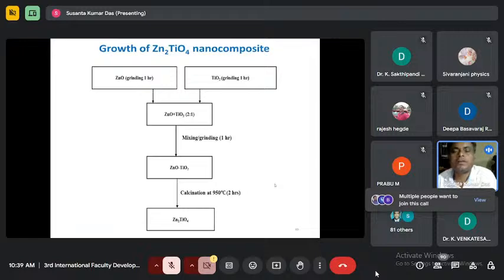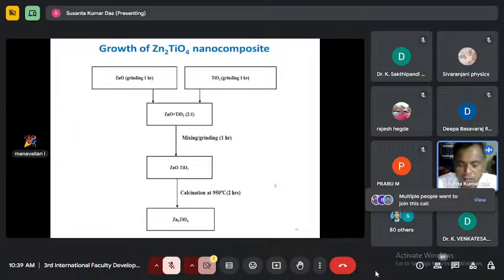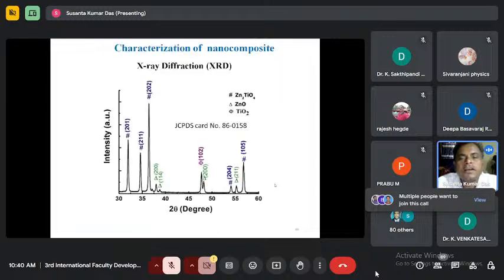I'll show you this, but just see the method. This is the solid state reaction method that we have adopted. Probably many of you know. In the solid state reaction, you have to grind the materials in a wet medium, like acetone also. Then you have to go for heating at very high temperature, like we had taken 950 degrees centigrade. Then we went for the XRD of the material.